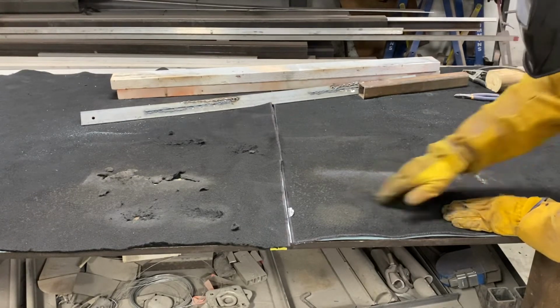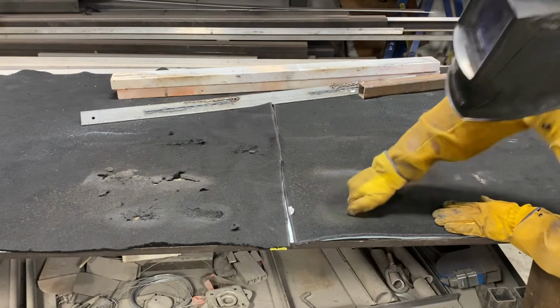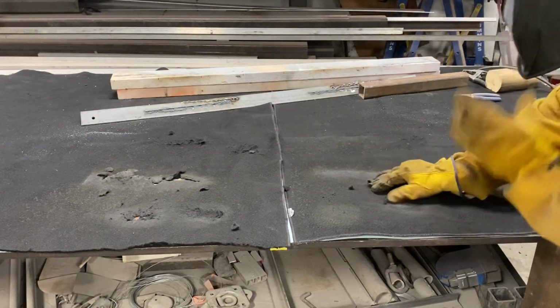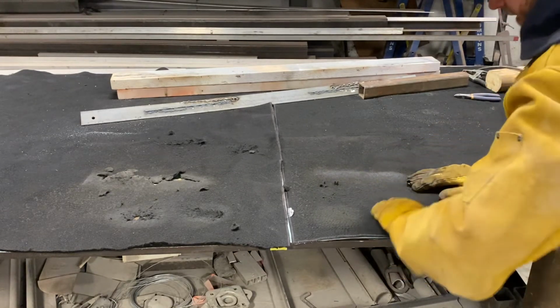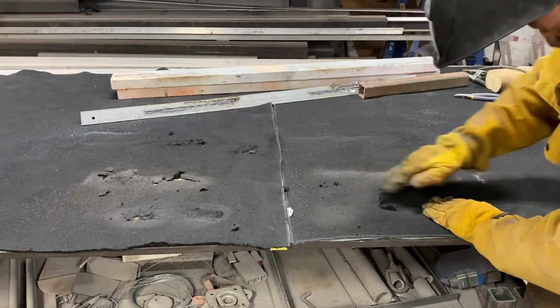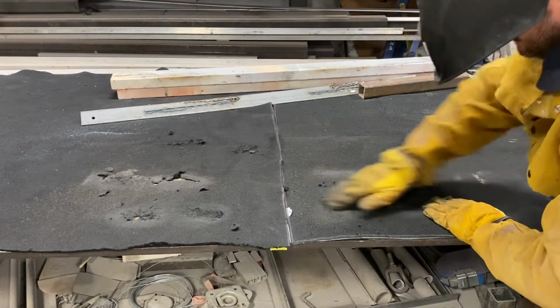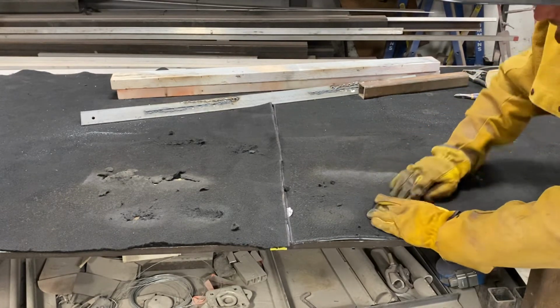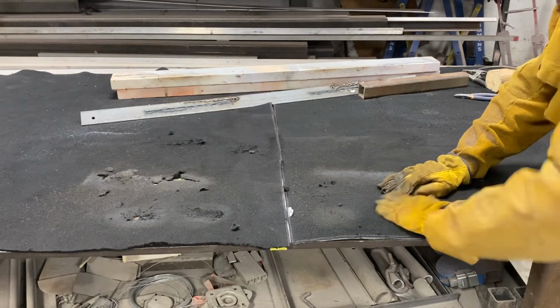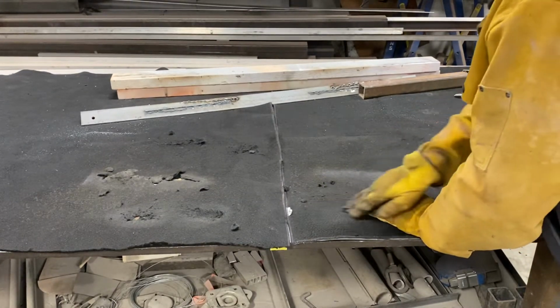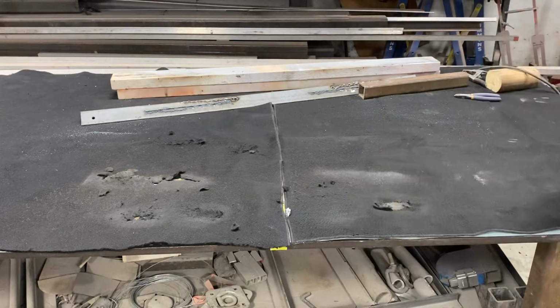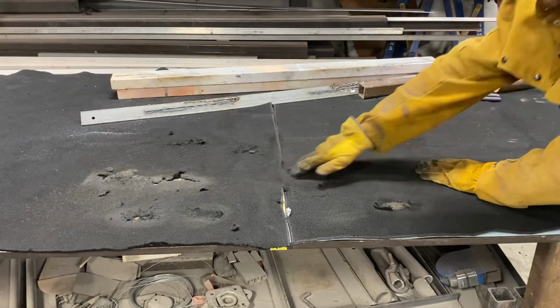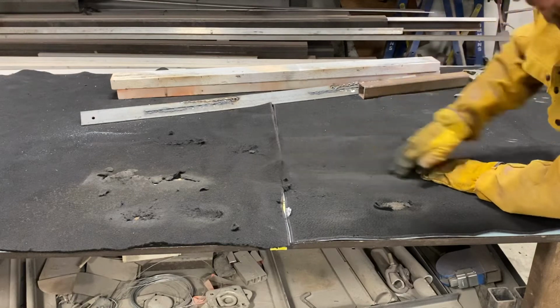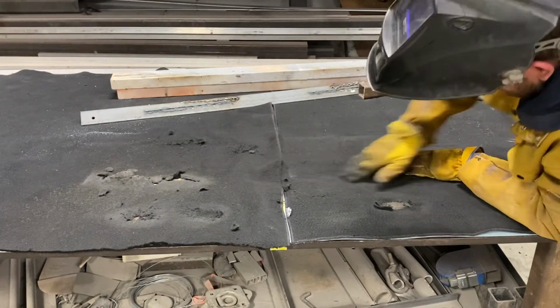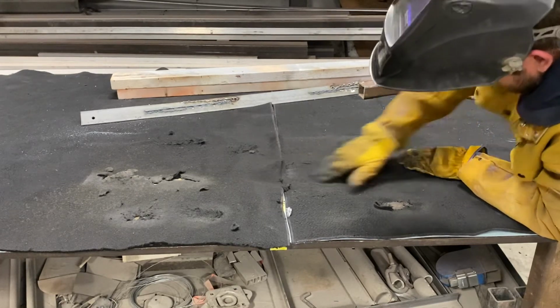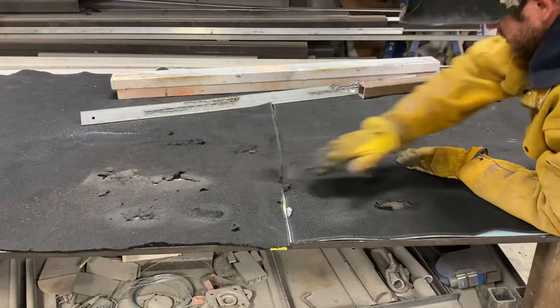Now on the 3-layer, I can get it rubbed down to the fiberglass, but then it stops. And here where we just hit it with 15 seconds, it's still great. Let's see here where we hit it with the torch. You can see it's breaking that top layer up a little bit. But once I get through that very first layer, I mean, we're not even down to fiberglass mesh yet.